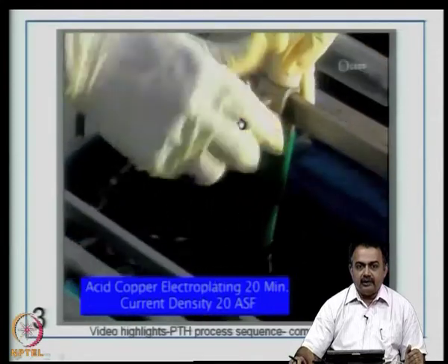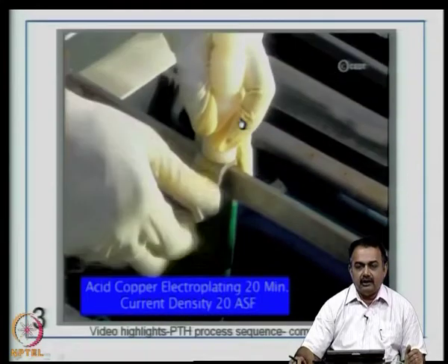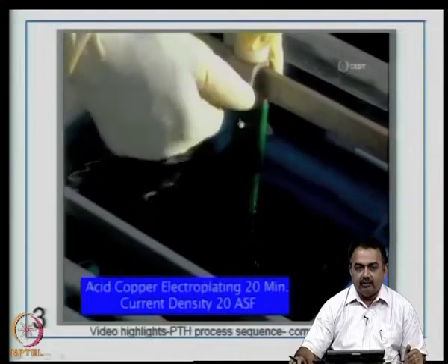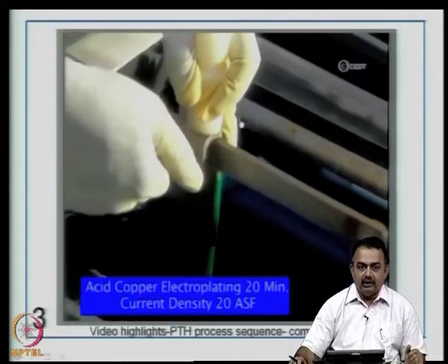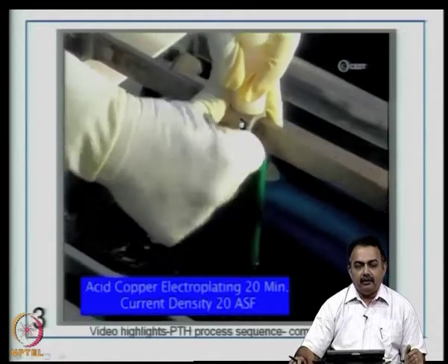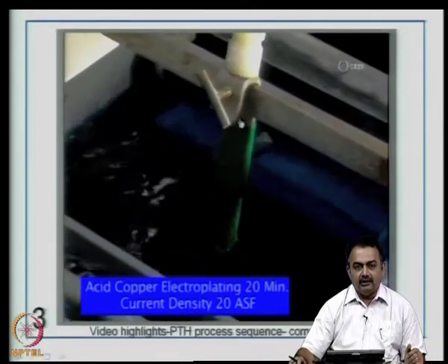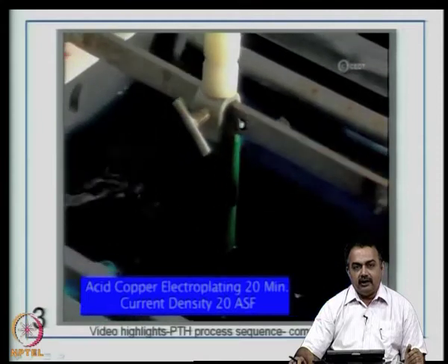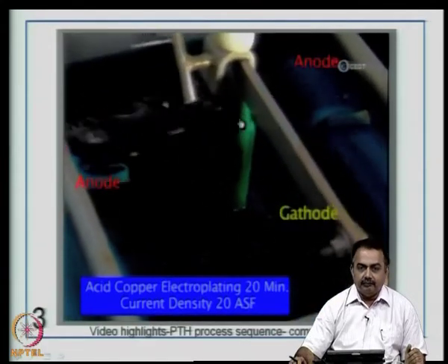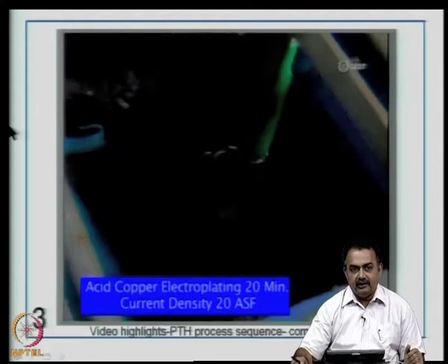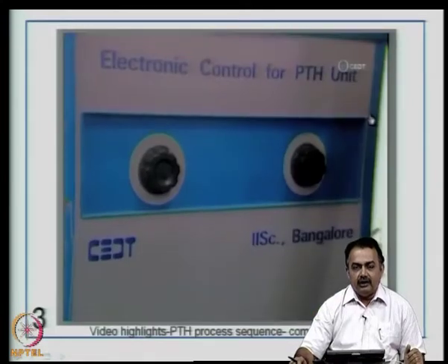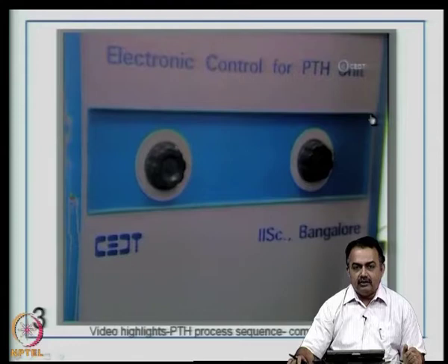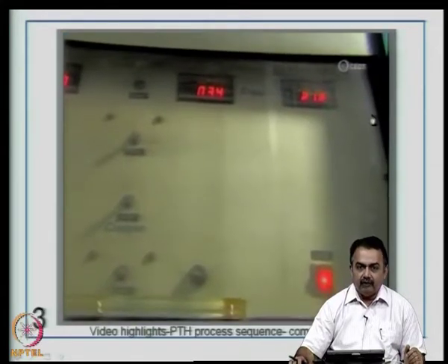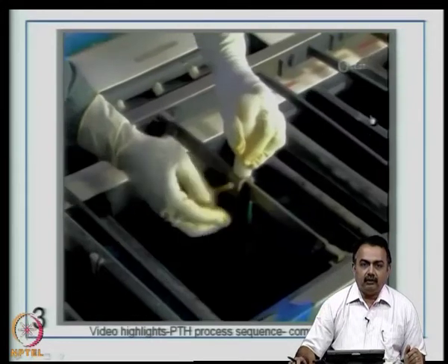Okay. Now, here you see that the technician is now introducing the jig containing the panel, the printed wiring board, which is the cathode, into the copper plating bath, and then the current density of about 20 amperes per square feet is now activated for the plating bath. So, you have two anodes on either side, here as well as here. You have the anodes in a bag, so that you get high purity anode getting into the electrolyte.